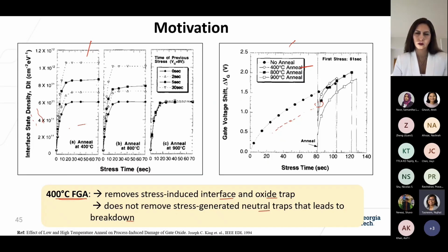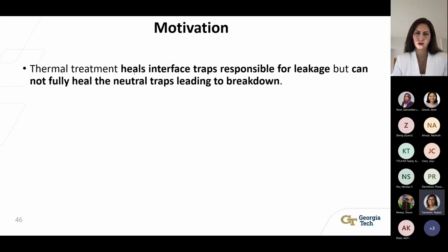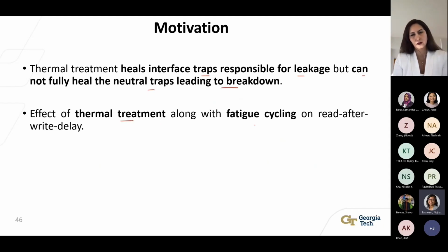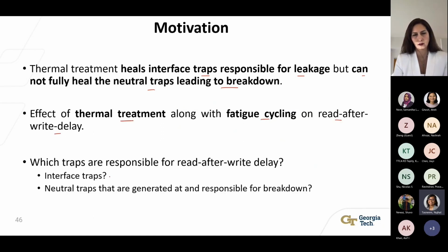So again, to reiterate, from this paper, we learned that thermal treatment can heal interface traps responsible for stress-induced leakage, but cannot fully heal neutral bulk traps leading to breakdown. So this is why we try to observe the effect of thermal treatment along with fatigue cycling on read after write delay, because we wanted to understand which traps are responsible for this read after write delay. Is it the interface traps or the bulk neutral traps that are generated at fatigue and responsible for breakdown?